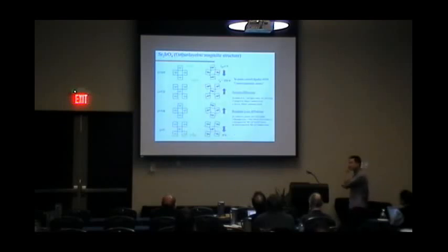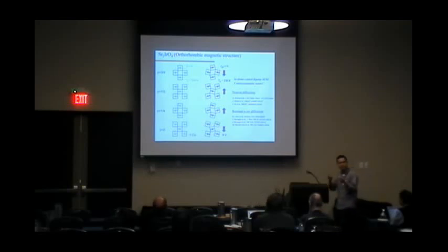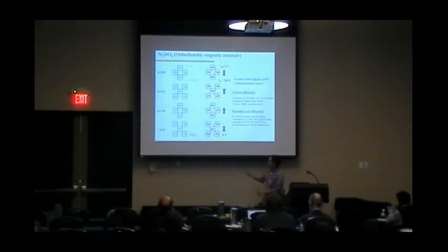Magnetically, they're also remarkably similar. So in the cuprates, at least in the parent phase, below about room temperature, you get this antiferromagnetic order and spin-half degrees of freedom on each site. And in the iridate, because of the strong spin-orbit coupling, you can no longer think about spins alone, but you can think of J effective angular momentum half degrees of freedom that are localized on the iridium sites. And similarly, below somewhere around room temperature, these J effective equal half moments order antiferromagnetically, just like in the cuprates, again with the one revision that these moments are going to point along the cardinal direction of the octahedron.